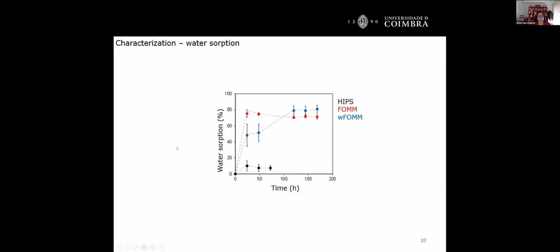Okay, then we went to water sorption. And of course, you have here in black HIPS, FOMM in red and washed FOMM (wFOMM) in blue. We must consider this with some care. Why? Because when you have foam, not washed foam, they are taking water, but at the same time they are losing the PVA. So you have a balance between these, and if you do this in a non-continuous flow of water, always in the same volume of water, you do not have PVA being leached out because it reaches an equilibrium with the